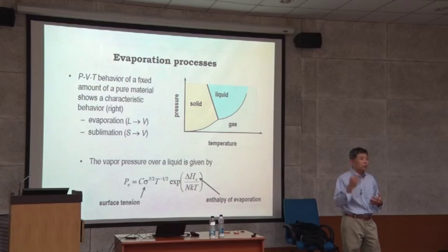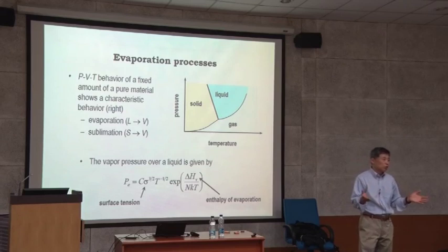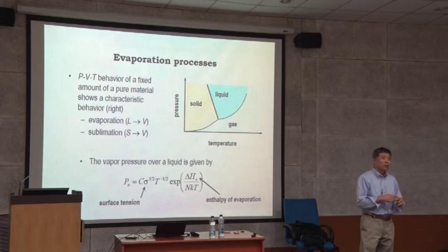UV, completely transparent. Complete transparent, no absorption. If there's no absorption, then you cannot ablate it. So with anything where your band gap is huge, like magnesium oxide or sapphire, you have to use a ceramic target. In ceramic, the absorption comes from all the grain boundaries, and it's basically opaque. But single crystal is not opaque. So for lanthanum aluminate, roughly 5 eV, and strontium titanate, 3.2 eV, those things you can do PLD with a 248 nanometer excimer laser. But if you go to 7 or 9 eV, a wide band gap, then you cannot do it.